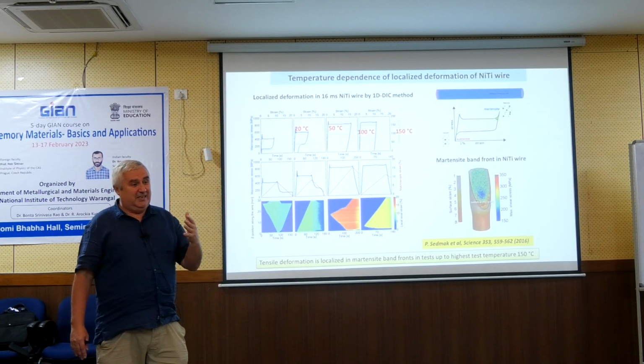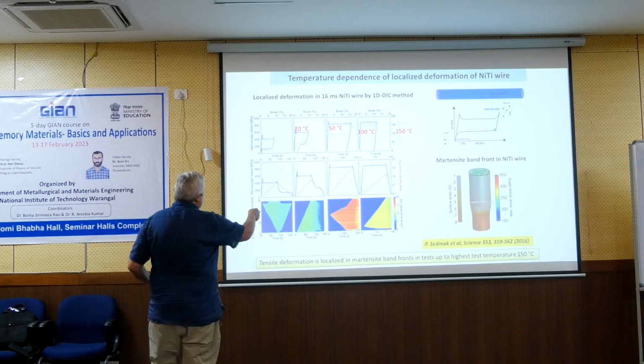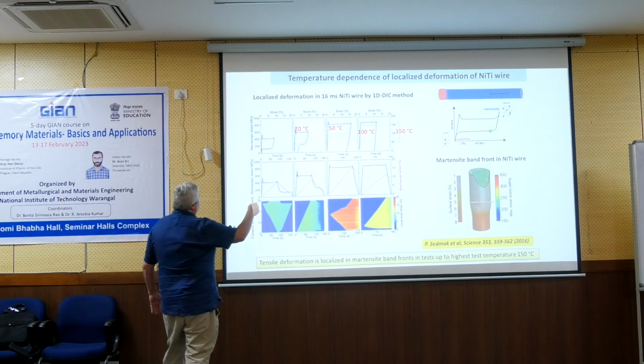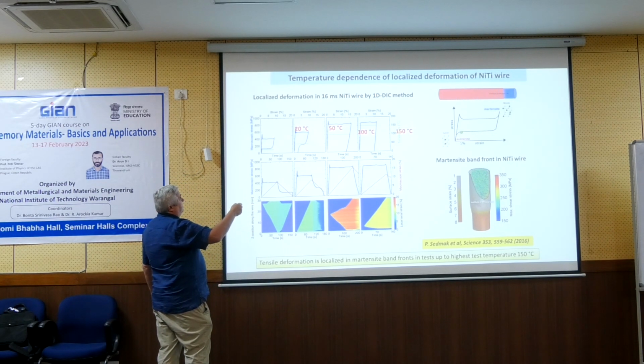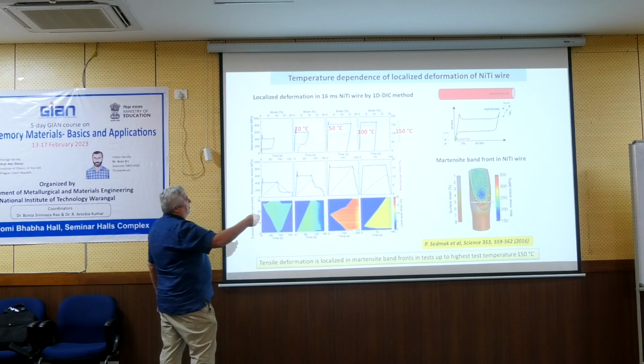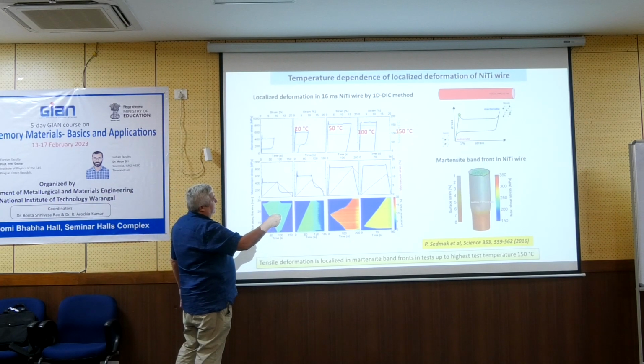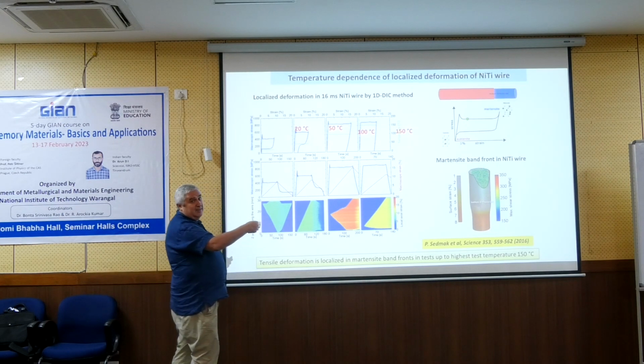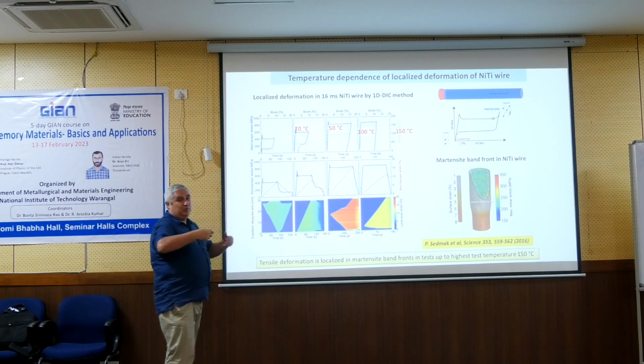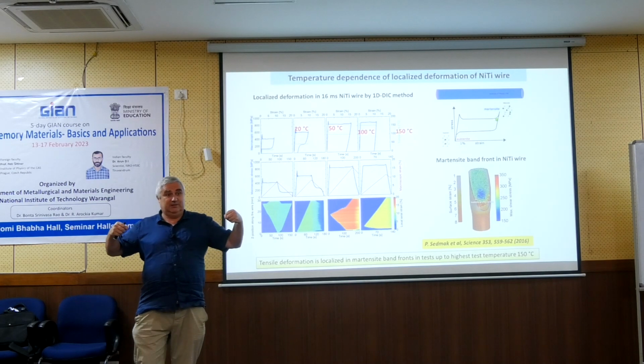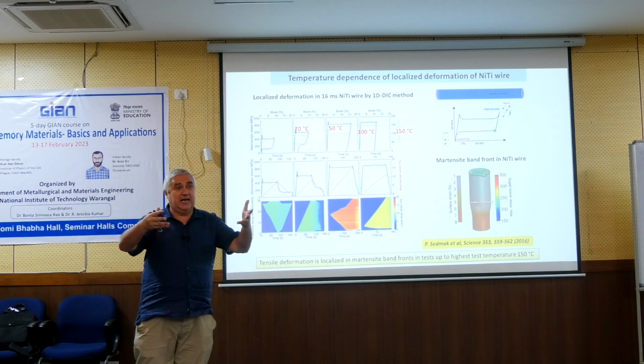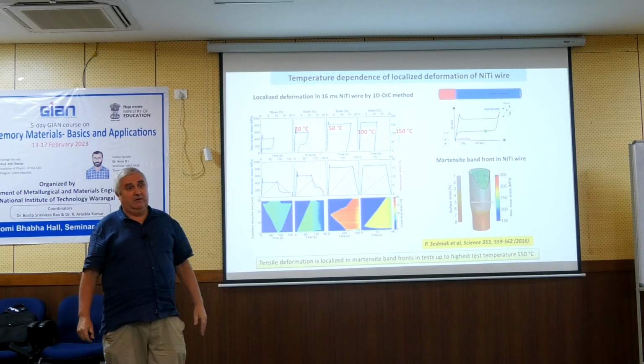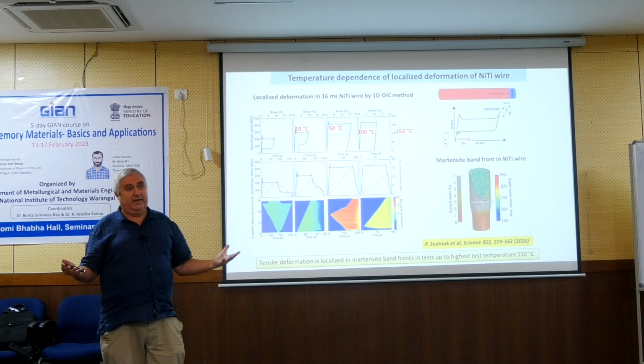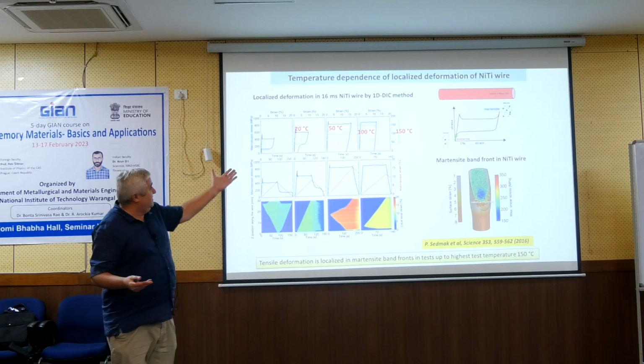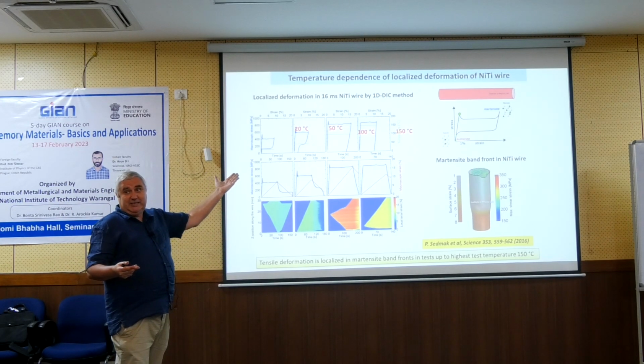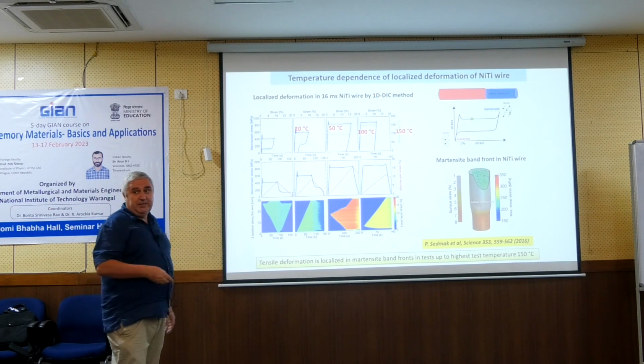You clearly understand that in this case only a small amount of energy is dissipated, so the area is small. But in this case, probably you don't have even the end. So much more energy is dissipated if you do stress-induced transformation at high temperature. And then you may ask why, and we would have to explain why more energy is dissipated. Because there are a lot of other processes which accompany the Martensitic transformation at high temperature.